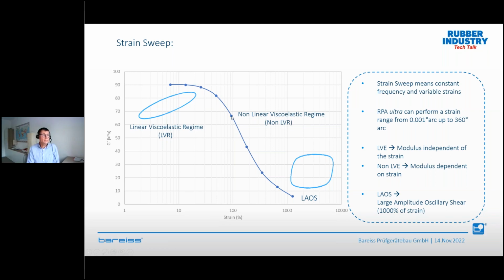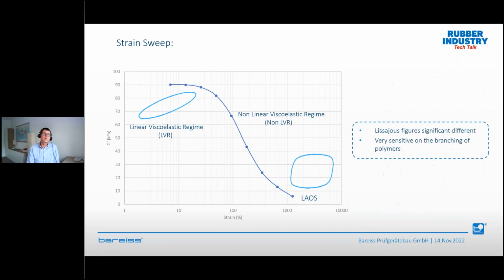That means you are increasing the strain, but the torque will not increase at the same time. And when you go to a very high strain, around 1000% strain, you go to LAOS. It's called LAOS, large amplitude oscillatory shear. I will explain it a little bit later in this presentation. So this is something where you can see what we have. The Lissajous figures are significantly different, and the LAOS test is very sensitive to another component which is important in polymers: the branching of a polymer.